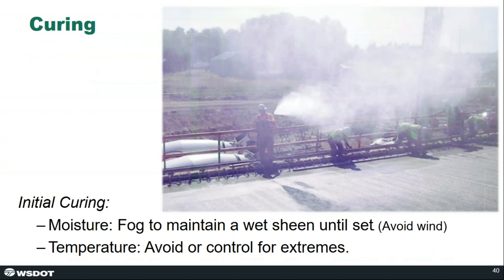So what are the steps that we specify? The first step is the initial curing after the finishing machine passes. We've moved to a fogging requirement. So the contractor has to fog sufficiently to maintain a wet sheen on the top of the concrete until the final set has been reached and we can install a final curing system. We definitely want to avoid windy days if we can. High winds are going to completely negate the effect of foggers, and dry conditions or dry weather makes this even more challenging.